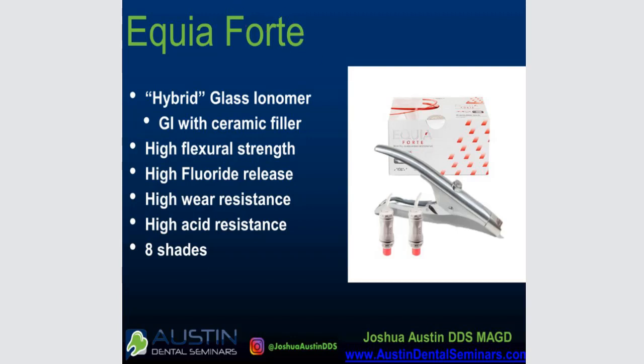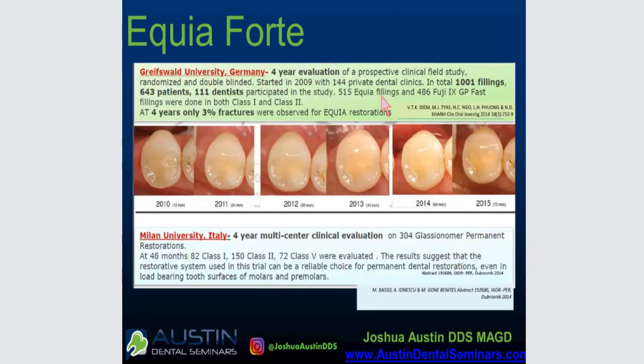And so where I would use Equia Forte is caries control type of situations. This is the material I used on Corey, who had the super sensitive class 2 that we redid, because this material will actually hold up pretty well in a class 2 scenario. And this material also works really well in a class 5. This material works really well in a core buildup. Pretty much anywhere that we've talked about it, Equia Forte works great.